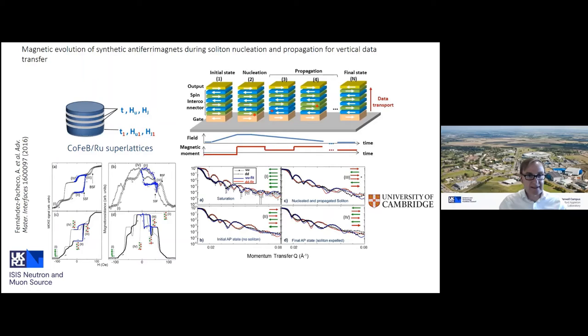And their natural ground state is for them all to be antiferromagnetically coupled, okay? We can then apply a field pulse and actually flip one of these layers. And you can see here now, we've flipped this layer. So we've basically got an information store. This is a little piece of information. We can apply another field and flip it up. And again, and we can move it through the stack. So we've got basically a shift register where we can move information and therefore transport data through this structure.